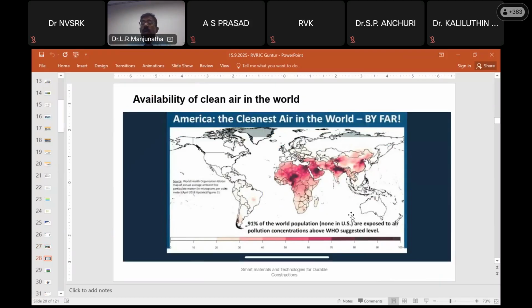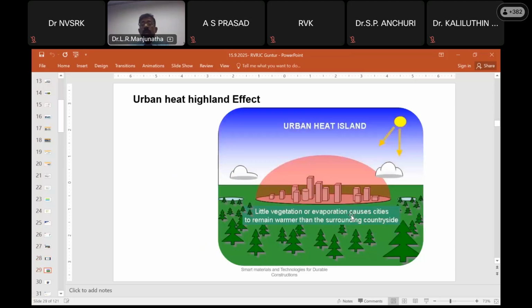The maximum pollution is happening in India, African countries and China. Other places are relatively okay compared to these countries, because more and more consumption of cement and development is happening in these countries, where they don't have much ready mix plant operation and still make concrete as site mix concrete. I already talked about the urban heat effect: cities are getting warmer compared to the surrounding area, with a temperature gradient of 2 to 3 degrees centigrade. I studied Bangalore, where temperatures have gone up by 1.5 degrees centigrade compared to the last 20 years, because of the concrete jungles we are creating. There's no passage of airflow through the centers.